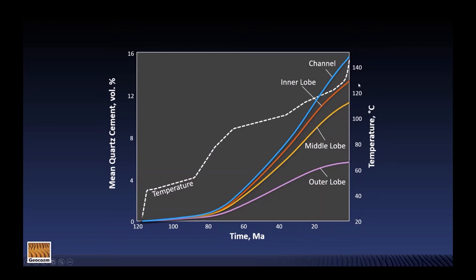Well, it comes back to that effect of the detrital clay that we were talking about before. Now, in the channel, we have very little in the way of that detrital clay. And so we have nice, big, juicy, intergranular pores. So when the quartz overgrowths nucleate on the pore walls on these quartz grains, those overgrowths can grow over the entire extent of nucleation domains, and therefore they can grow at a fast non-euhedral rate into that pore space.